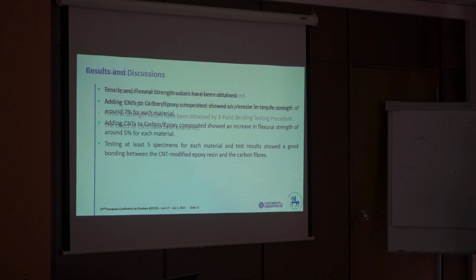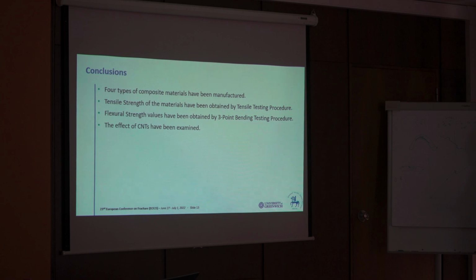And then again, according to the standard deviation and our test results, we can say that the test results were quite similar to each other. And so we can say that there was a good bonding between the carbon nanotubes and the epoxy, so there wasn't any problem within the manufacturing part.